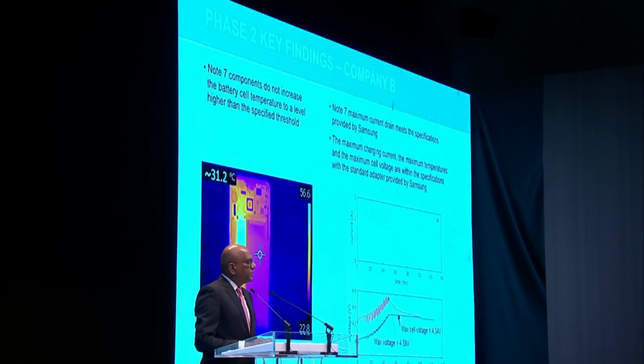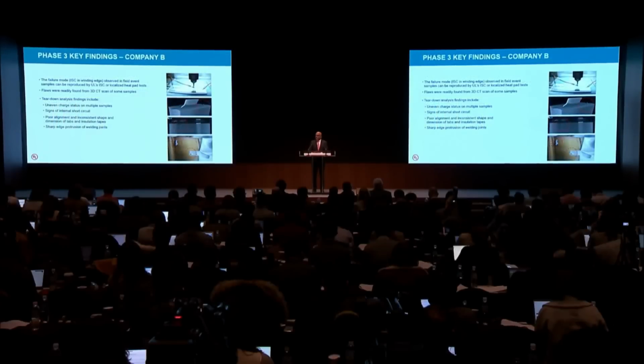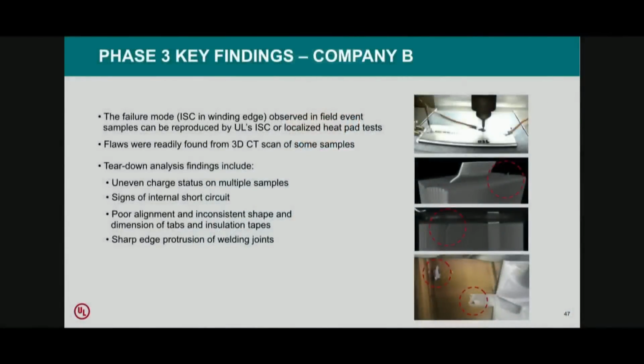The maximum charging current, the maximum temperature, and the maximum cell voltage were all also within the specification with the standard adapter provided by Samsung. For phase 3 of Company B batteries, we found that the failure mode observed in the field event samples can be reproduced by UL's internal short circuit test or localized heat pad test.